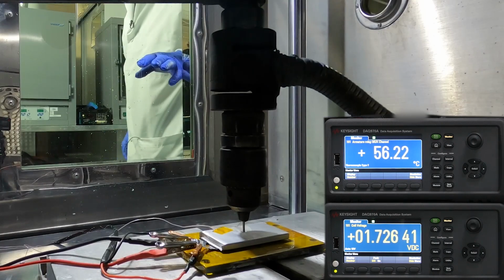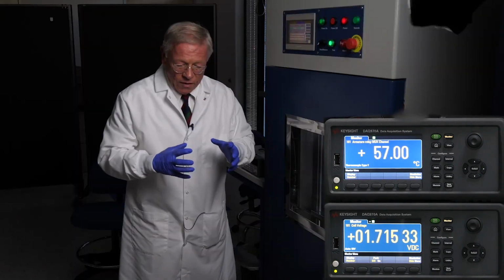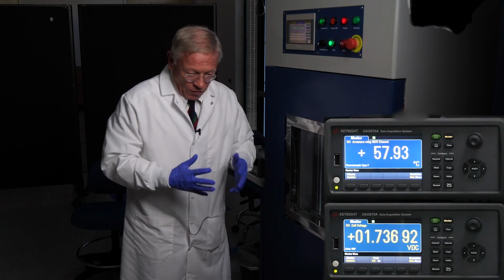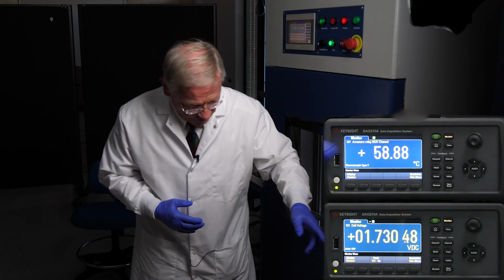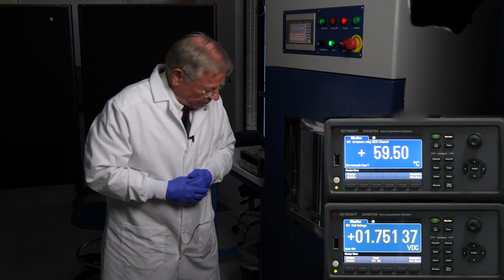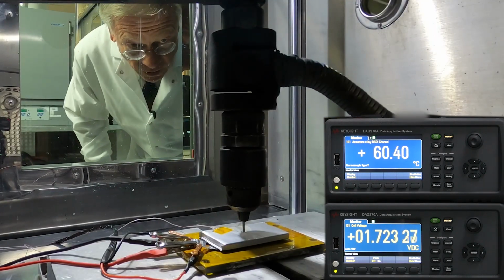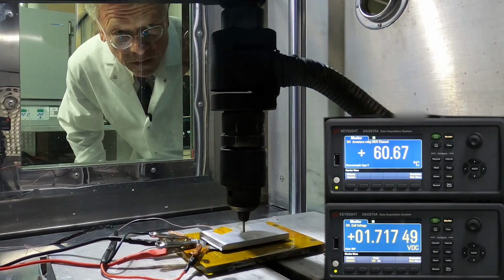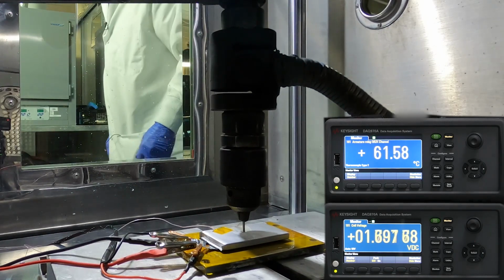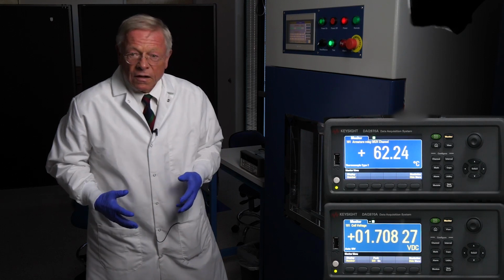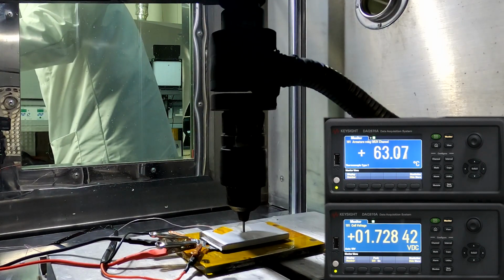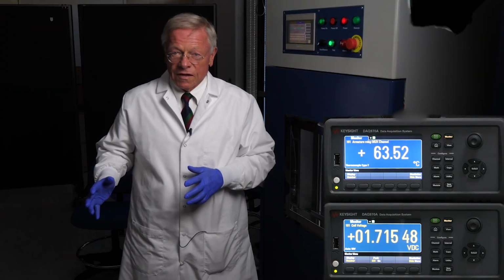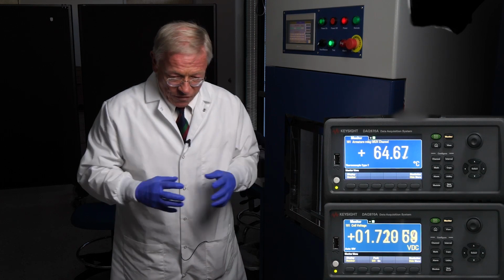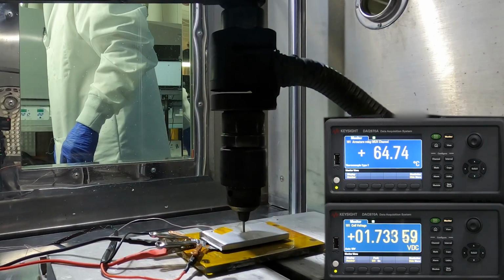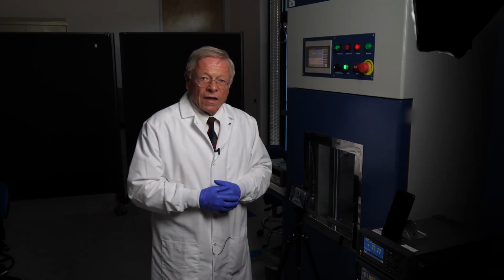By the way, this battery will degrade at about 170 degrees. That's when the separator melts. And that will cause an even quicker reaction. But this thing is 110 degrees below that temperature, and it will never get to that temperature. Can't see much. That, of course, is what we expected, that BrakeFlow would prevent burning. And people have been working on this since the lithium-ion battery got invented. This has always been a problem because there's so much energy in the battery. You have to have a mechanism for releasing it slowly because it will heat things up. So right now, it's over and nothing happened.